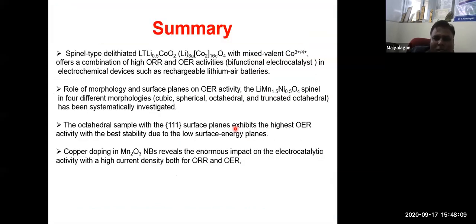So the summary is we have seen delithiated lithium cobalt oxide with mixed valent cobalt 3 plus and 4 plus, and it shows both ORR and OER as a bifunctional electrocatalyst in lithium-air batteries. And morphology also plays a role in all these catalysts, whether the 111 planes, which plane is showing. Also copper-doped manganese oxide shows you can utilize it in metal-air batteries.